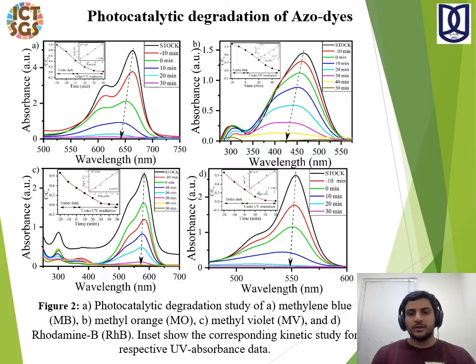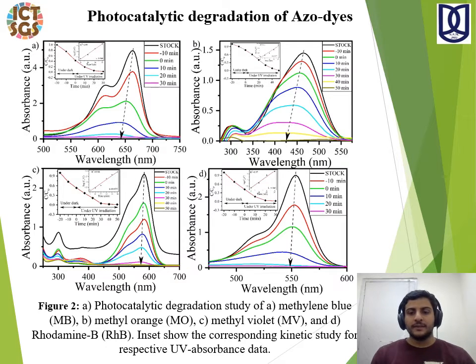This is the photocatalytic degradation of azo dyes. Part A shows the degradation of methylene blue, B shows methyl orange, C shows methyl violet, and D shows rhodamine B. In all of these studies, no co-catalyst, acid, or base was used — just the nanoparticles in the dye solution exposed to UV light irradiation. Methylene blue achieved 99% degradation in 30 minutes, methyl orange in 50 minutes, and methyl violet in 50 minutes. The inset of each shows the corresponding pseudo-first-order kinetics.